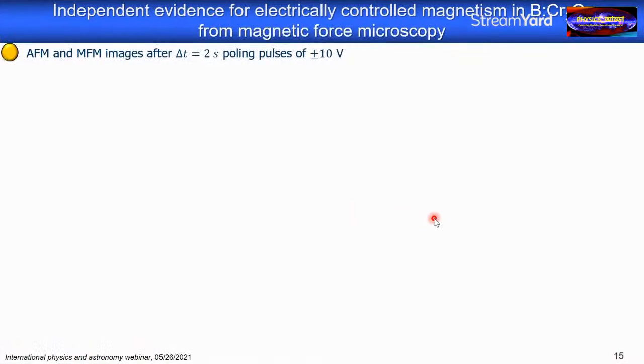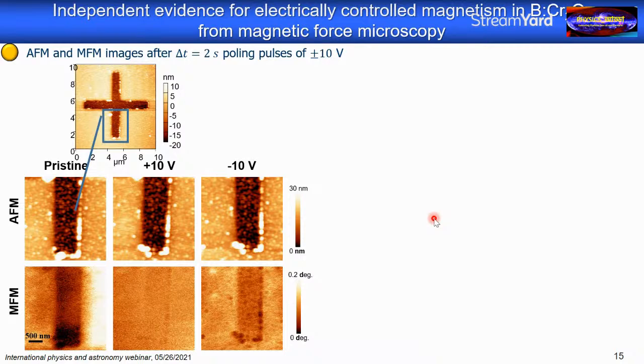And maybe an even better independent check is a check with a completely different method. We wanted to see if we change the orientation of the magnetization by applying an electric field, we should be able to see that in magnetic force microscopy. And again, this is what my colleague Alexei Gruberman did for us in this context. So here you see an AFM image, atomic force microscopy, so the topography of the palladium Hall bar on top of the chromia. Here, this is just this part of this Hall leg in the pristine case. And below, you see the magnetic force contrast. You see what happens when we apply a positive voltage. The contrast basically disappears. When we apply a negative voltage, the contrast reappears. That was a eureka moment where we said, okay, we really switch here something that is magnetic by voltage.